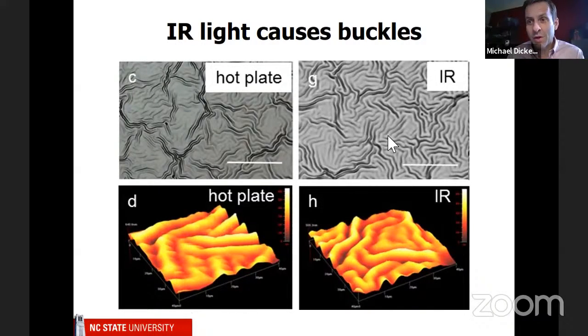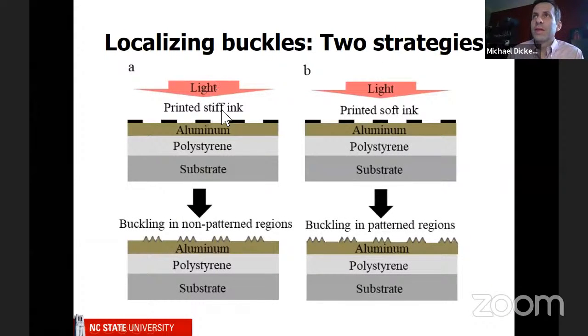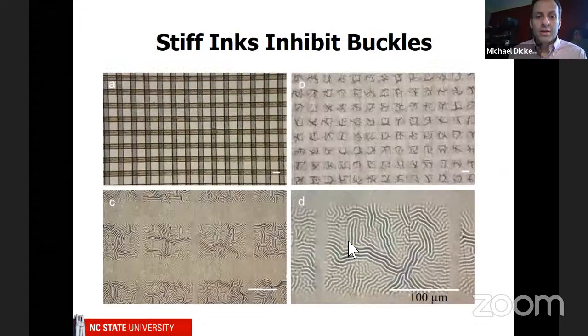And this is where I was wrong. What is happening is that the ink is sufficiently stiff that wherever you put the ink, it prevents the film from forming those wrinkles. The wrinkles actually form in the places where there's no ink. So if that's true, based on our hypothesis, if we put a soft ink, the exact same structure but softer, then we should be able to get wrinkles wherever we put the black ink. So indeed, the black ink from an inkjet printer is sufficiently stiff that it prevents wrinkles from forming.